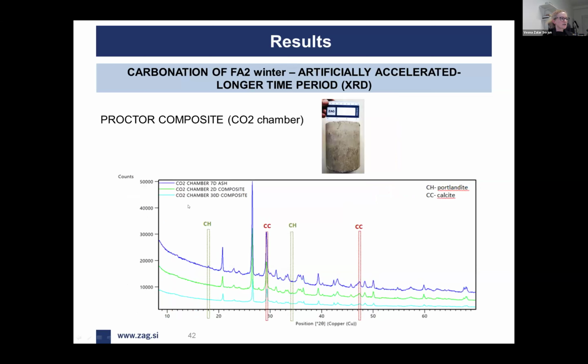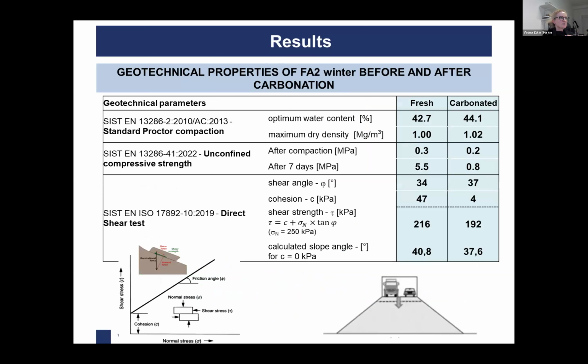On the other hand, when checking CO₂ chambers, so lower relative humidity, again, nothing much is happening also in the Proctor composite itself, and the results are practically the same as when we were identifying the raw material itself, the ash itself. So some geotechnical parameters were also defined when using fresh and carbonated ash. There are some differences, and maybe the largest differences are in unconfined compressive strength, where the fresh ash achieved 5.5 megapascals, while carbonated only 0.8.